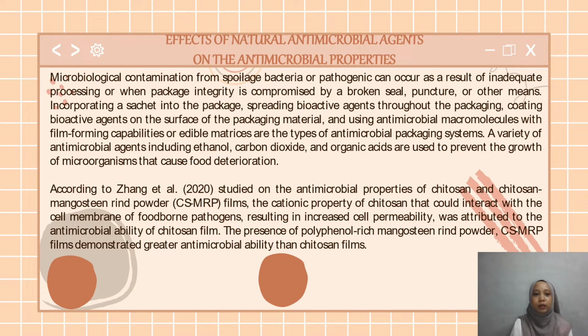A variety of antimicrobial agents including ethanol, carbon dioxide, and organic acids are used to prevent the growth of microorganisms that cause food deterioration. According to Zhang et al. 2020 study on the antimicrobial properties of chitosan and chitosan-mangosteen rind powder CSMRP films, the cationic property of chitosan that could interact with the cell membrane of foodborne pathogens, resulting in increased cell permeability, was attributed to the antimicrobial ability of chitosan film. With the presence of polyphenol-rich mangosteen rind powder, CSMRP films demonstrated greater antimicrobial ability than chitosan films.